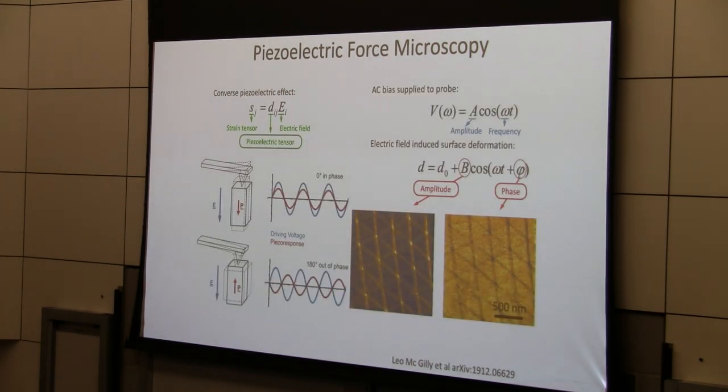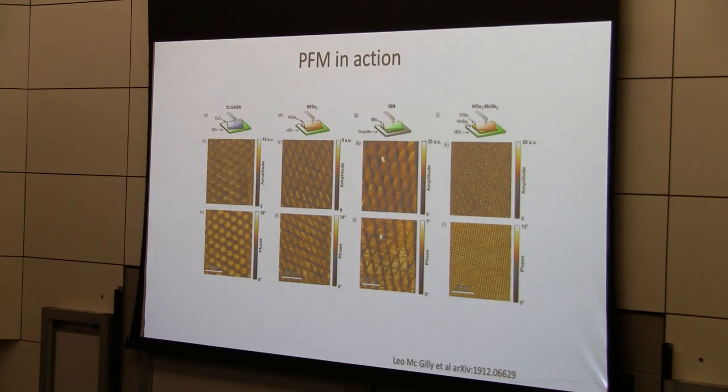It turns out that all of these moiré materials actually have a piezoelectric response, which you can see by applying an AC electric field to a simple AFM and measuring the response. And this is quite fascinating in and of itself. If you take graphene, a sheet of graphene has inversion symmetry, so it has no piezoelectric effect. But if I take two sheets of graphene, then exactly at the van der Waals interface, I do seem to develop a piezoelectric response. And I don't want to get into the details of all of this, other than to say that this technique is absolutely fantastic.